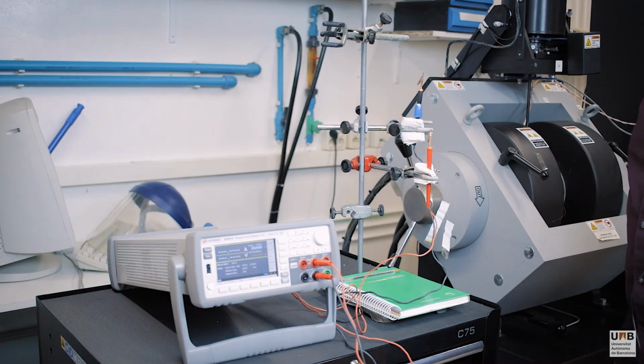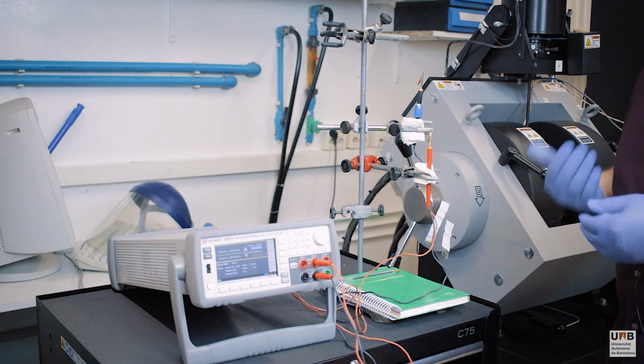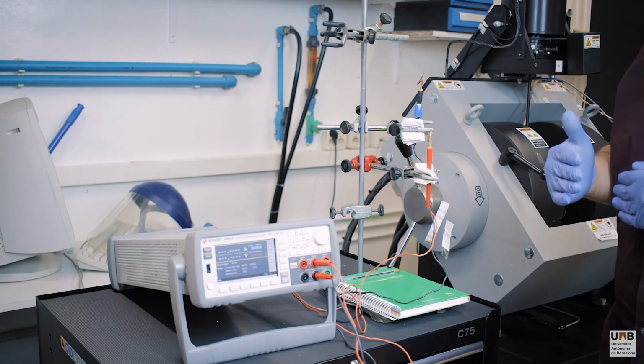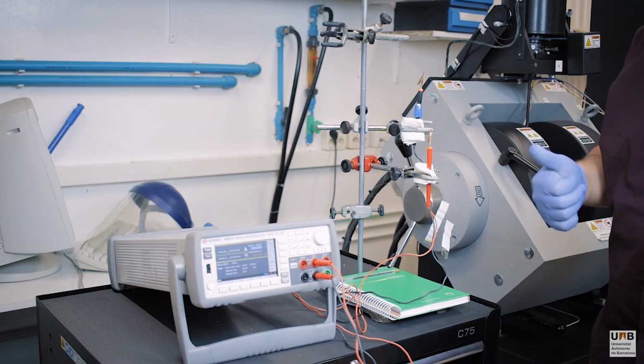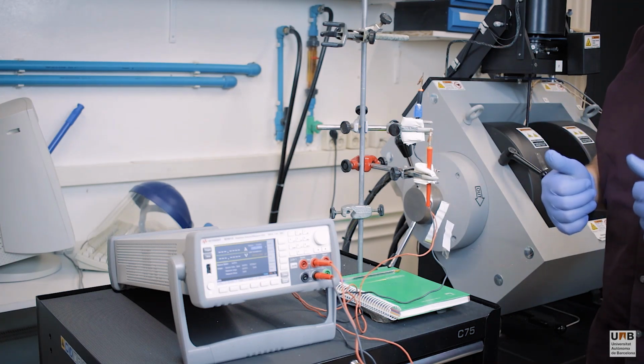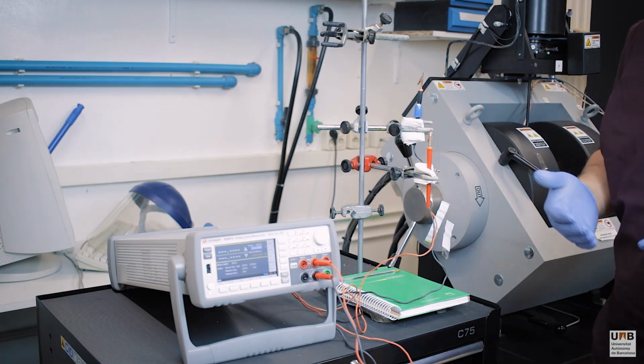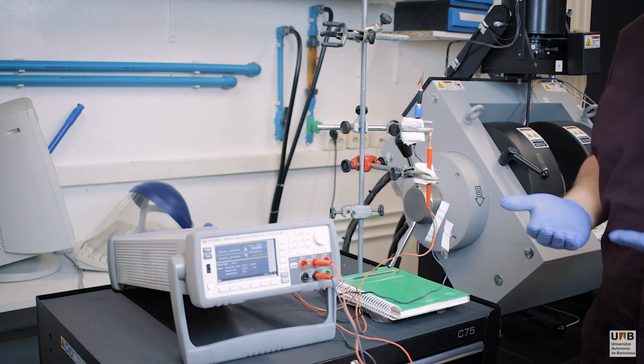So now we're going to start a magnetoionic measurement. For those of you who don't know, we're going to apply a voltage, and this voltage across the two electrodes will drive ions in and out of the sample, in this case oxygen out. And we should see an increase in magnetization because of the lack of oxygen and more metallic cobalt present.